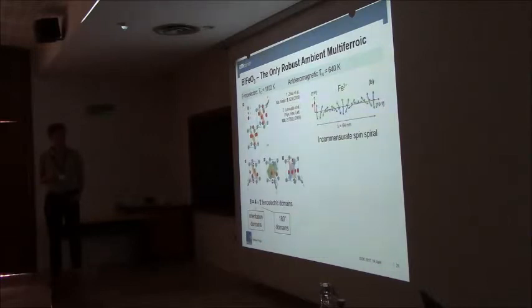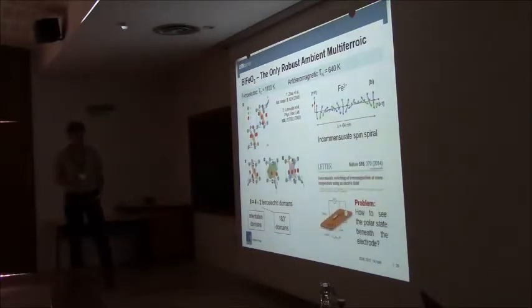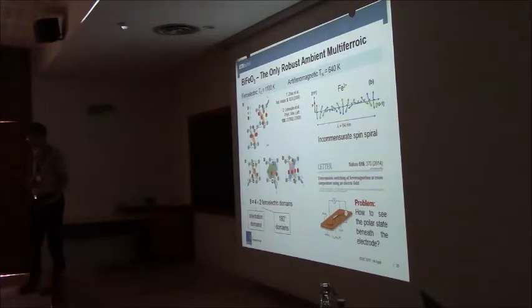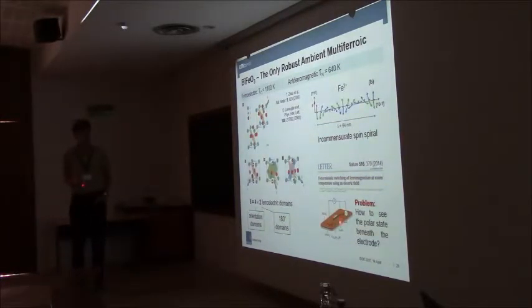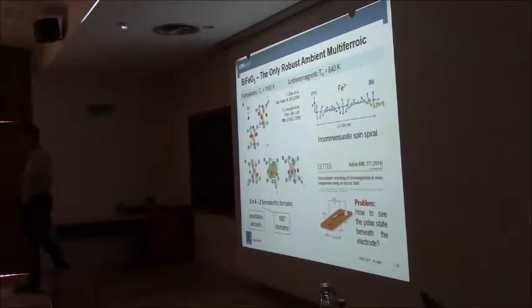Here now we have a different idea. So you have seen Ramesh's experiment. He says, okay, my bismuth ferrite is antiferromagnetic, but if I want to control ferromagnetism, convert it into ferromagnetism, I just put cobalt iron alloy on top. And the cobalt iron alloy couples to the antiferromagnetism of the bismuth ferrite, which then couples to the ferroelectricity of the bismuth ferrite. By applying a voltage contact, you can reverse the polarization in the bismuth ferrite, and thereby the antiferromagnetization, thereby the magnetization in the cobalt iron alloy.